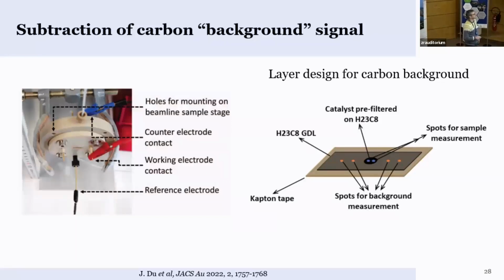So in this PSI design, we started to have a carbon film and to really have measurements at different places of the sample. So that's basically the catalyst sample, and that's only the carbon. And then to scan at different points, two at the sample where the catalyst is, and two where there's only carbon, but the carbon also experiences the electrochemistry, so that you can look at these points as a background that you subtract from the measurement.